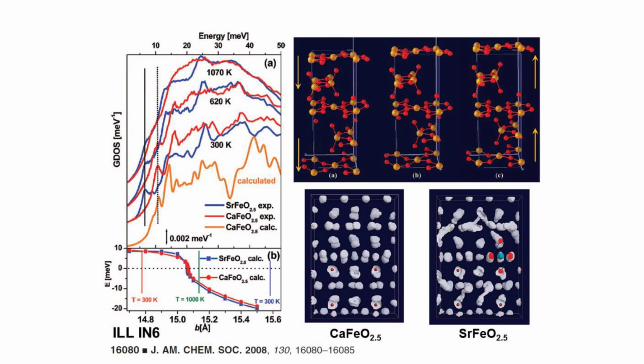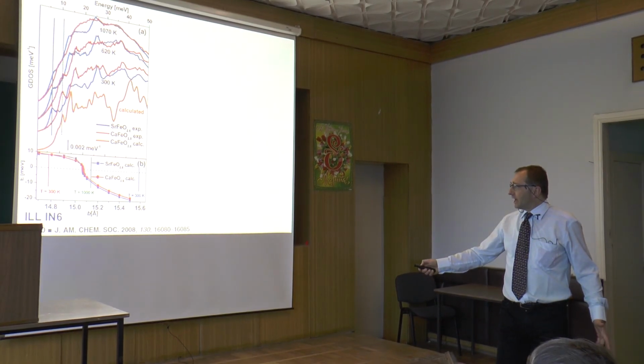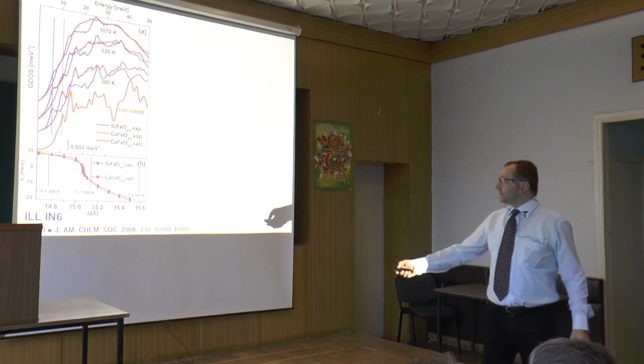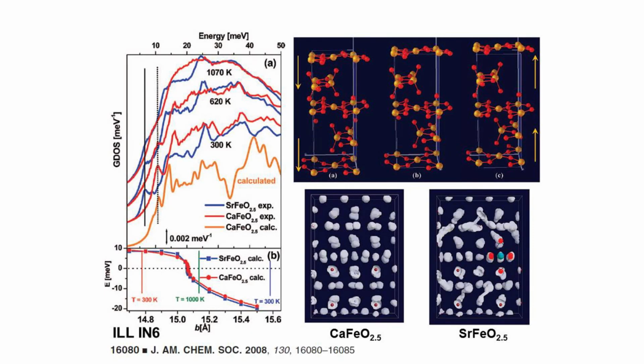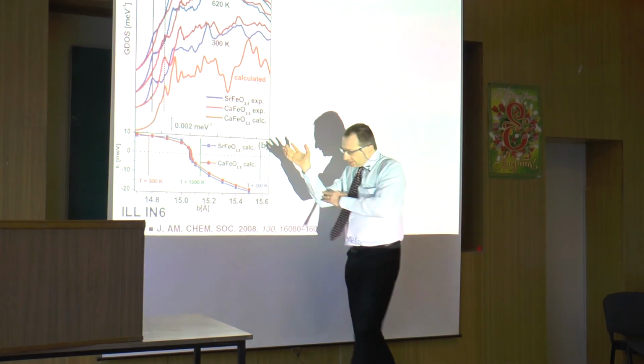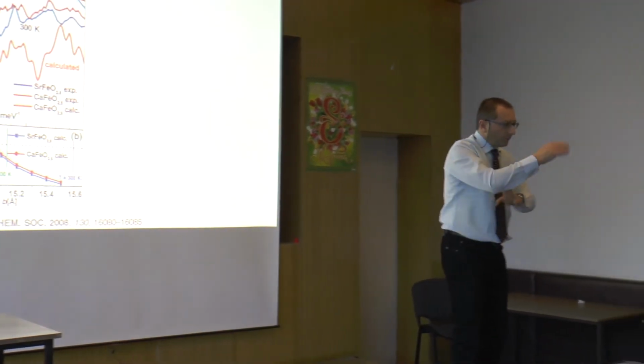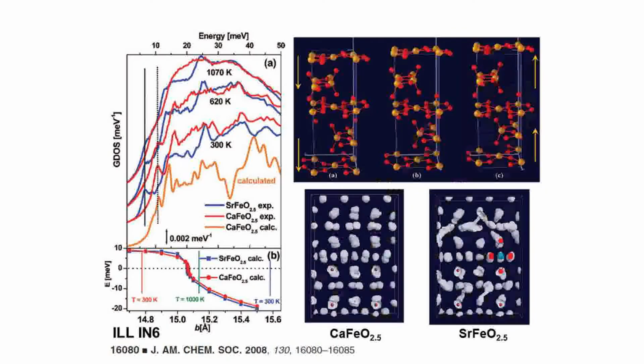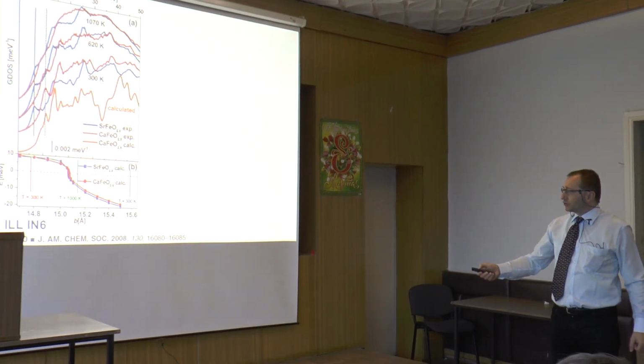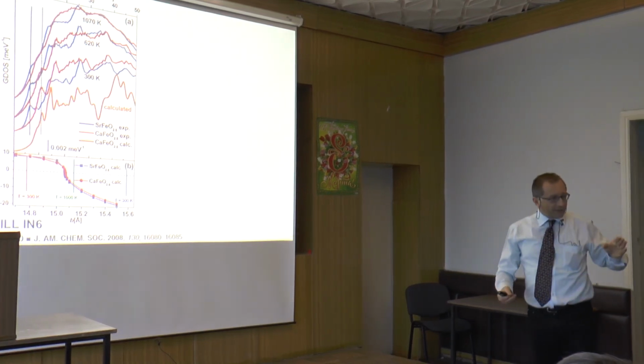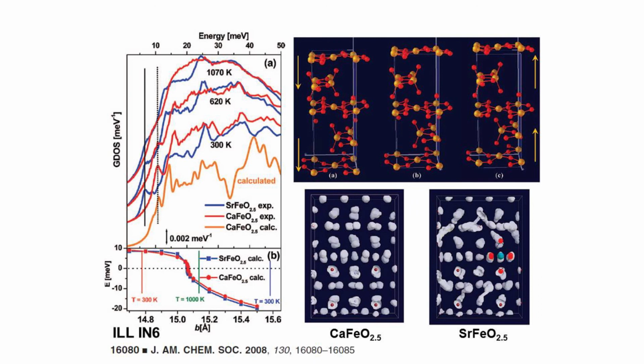But we see that the determining factor is the lattice parameter, because when the lattice parameter reaches values higher than 15.1 Angstrom, this mode becomes negative. What does it mean that it becomes negative? This means that this is no more a stable position. Okay? This means that when we reach this position here, the tetrahedra are allowed to switch from one position to the other. And if we look at the diffraction data, we see that the calcium iron at room temperature has this lattice parameter. So this mode is stable. This means that in calcium iron, the tetrahedral sites are not allowed to switch from one position to the other. So if the door is closed, it remains closed.